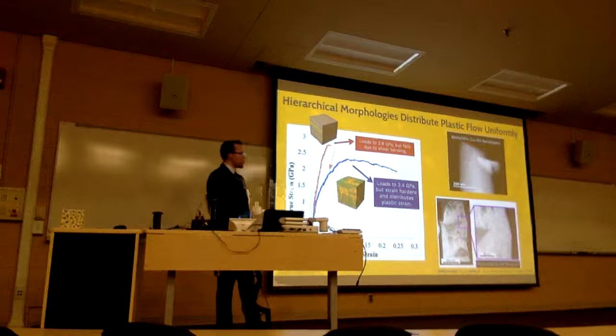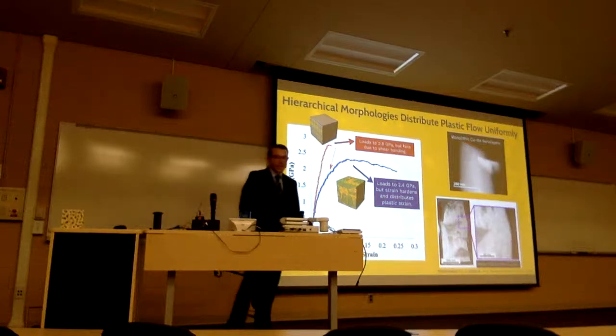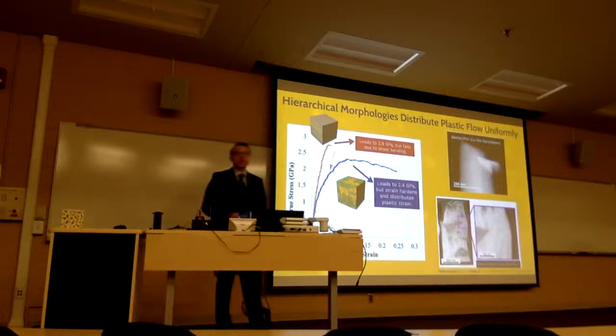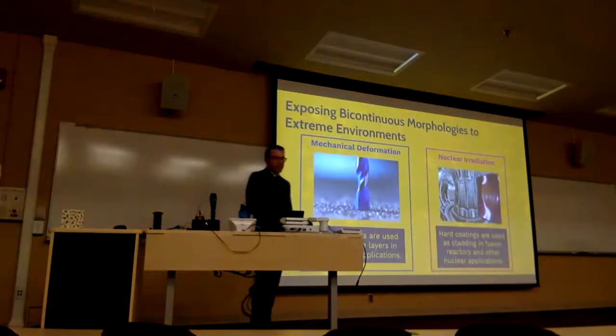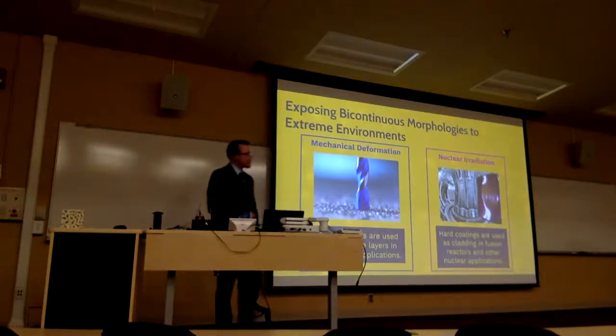The hierarchical morphology actually strain hardened at high strain rates and distributed plastic strain much more uniformly, and we didn't see examples of shear banding after compression. And the other environment, so that's the mechanical behavior of the sample.